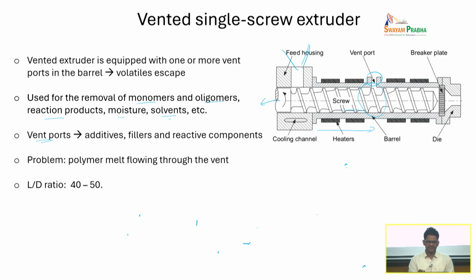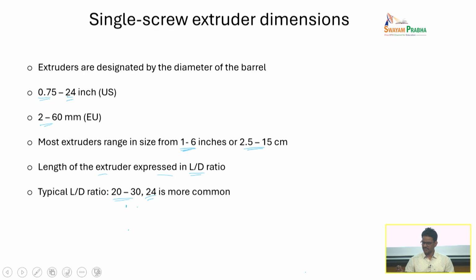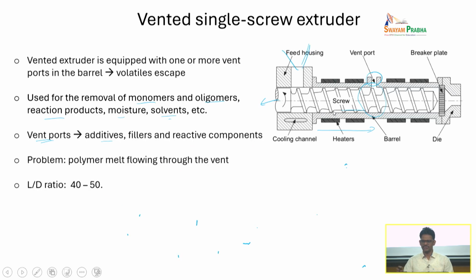Sometimes we can also use these vent ports to actually add extra additives. This polymer may not have any volatile compound, but if you have an extruder with a vent port, that vent port can be used to actually mix fillers and additives and other reactive compounds. Okay, for example, one option is to add the filler and other things in the feed hopper itself, but sometimes if you want to add something when the polymer is nearly in a melt condition, you can actually use these vent ports to introduce the filler and other blends and other additives.